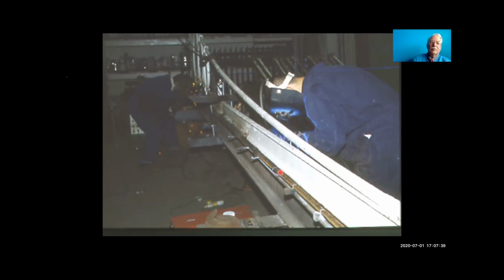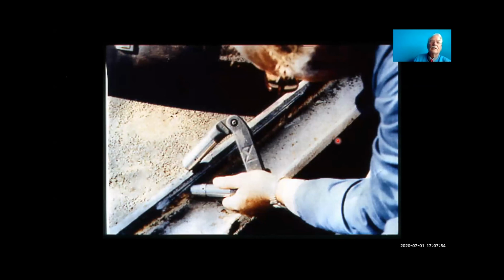Now, the problem is that we have a wrought iron with a longitudinal grain and a repair plate with a longitudinal grain, and the contractions of the weld tend to pull the grain apart. So you end up with tiny cracks. Here we are, we've laid down this truss now. There's the repair plate, there's the original T-section, and there is our weld running along the truss. And the cracks develop along the side of the weld or through the weld.